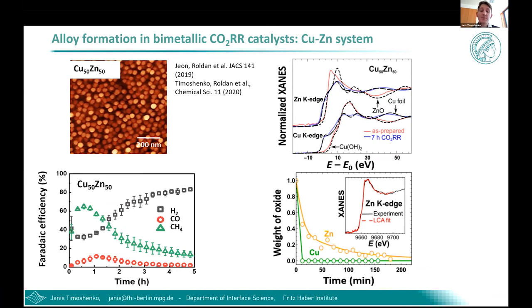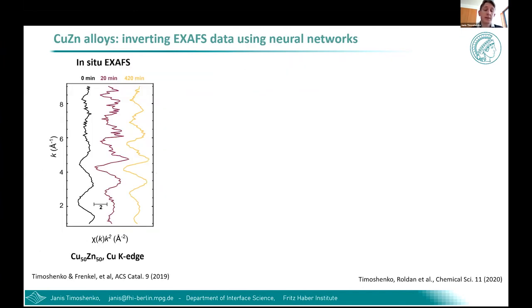So now we want to know what happens with the copper environment, which is supposed to be the active species here, during the slow reduction of zinc. To answer this question, we now look at EXAFS spectra. The challenge in studies of copper-zinc alloys, or other alloys which consist of metals that are neighbors in the periodic table, is that unlike the copper-silver or copper-gold case, the contrast between copper and zinc partial contributions to EXAFS spectra is quite low, so it's not easy to tell them apart. At the same time, we can still distinguish between copper-rich and zinc-rich phases of the material if we manage to extract accurate information about interatomic distances, because these are expected to be different in copper-rich and zinc-rich materials.